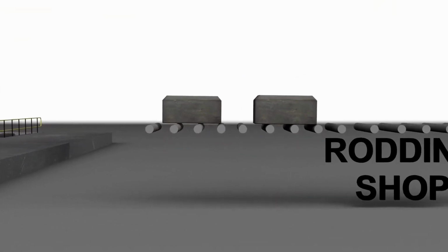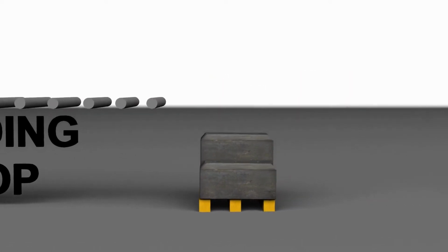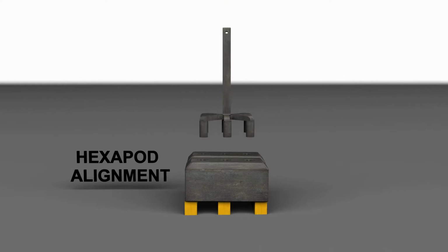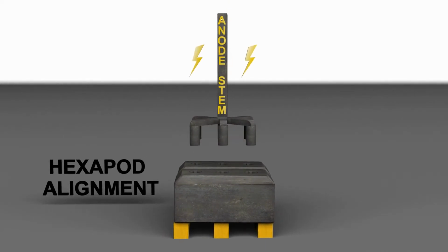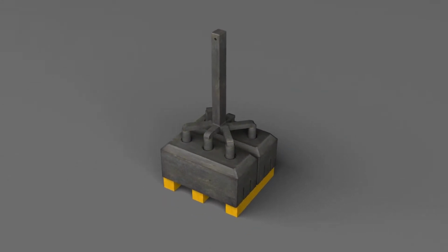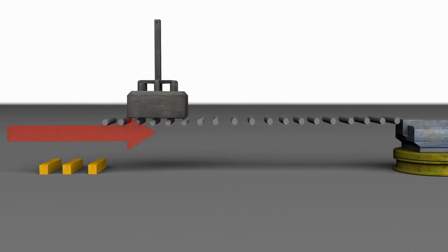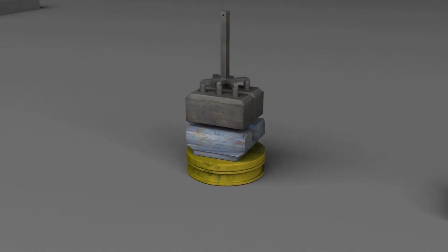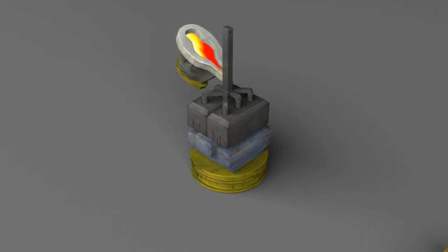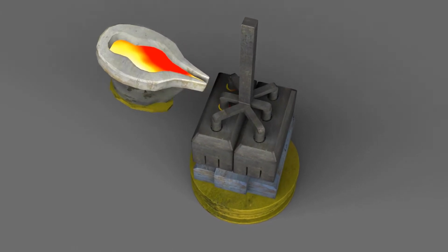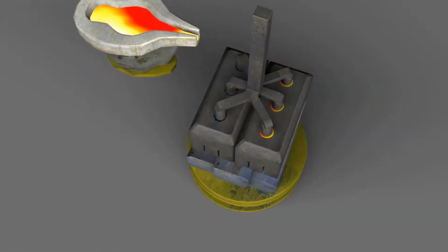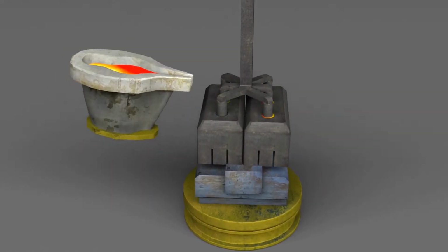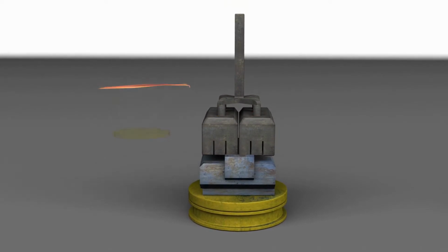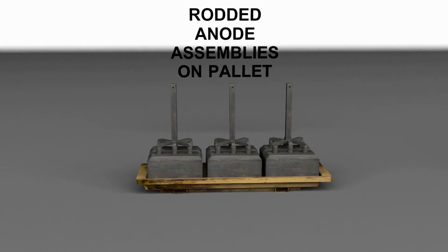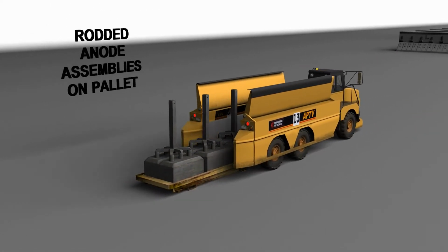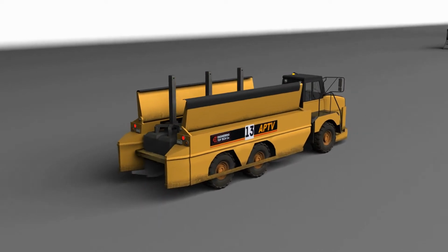The baked anodes now enter the rodding shop, where anode stem attachment takes place. The anode stem is an electrical conductor consisting of an aluminium rod welded to an iron hexapod. Each hexapod, meaning 6-footed, is automatically aligned with 2 anodes and then lowered so that its feet enter the holes in the top of the anodes, which are then cemented in place with molten iron. Rodded anode assemblies are now conveyed to the reduction plant by means of a special vehicle known as the Anode Pallet Transport Vehicle, APTV.